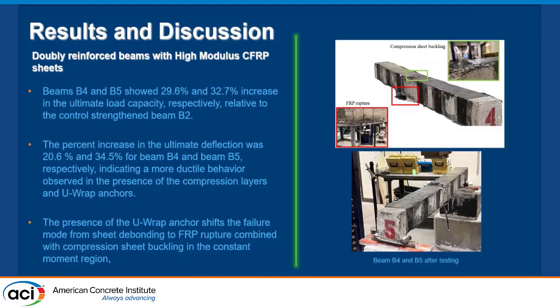So this is what I mean by the U-wrap. The U-wrap is a means of anchoring the tension FRP sheet. Normally, if we leave the FRP sheet without any anchoring, the crack debonding will start at the maximum moment region at the middle and propagate toward the end, and that will make room for the sheet to debond and to fail without achieving the maximum benefit. So we use this means of anchorage in order to provide a confined space for the FRP to stick to the beam and to utilize the full composite behavior between the FRP and the concrete.